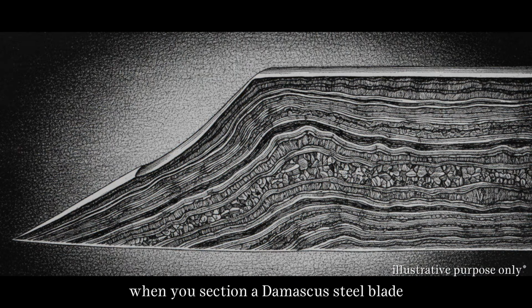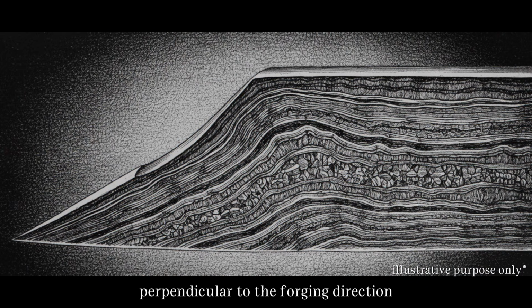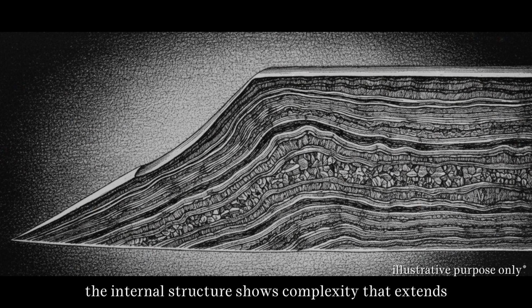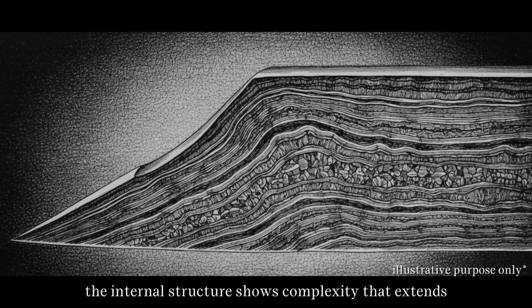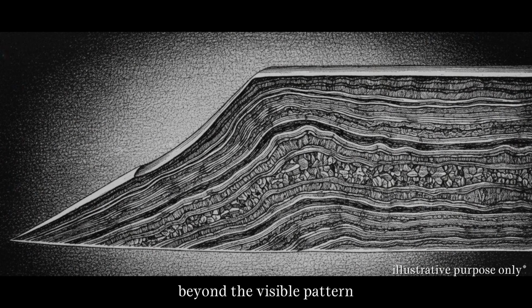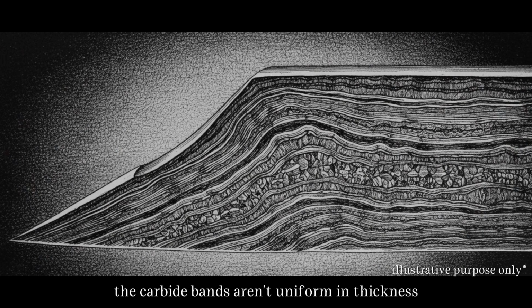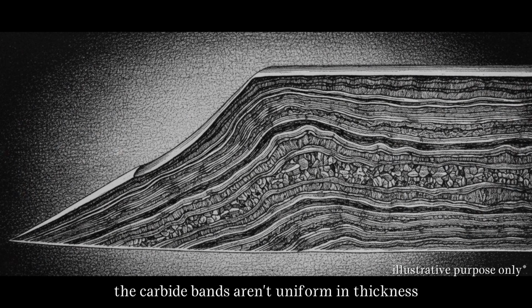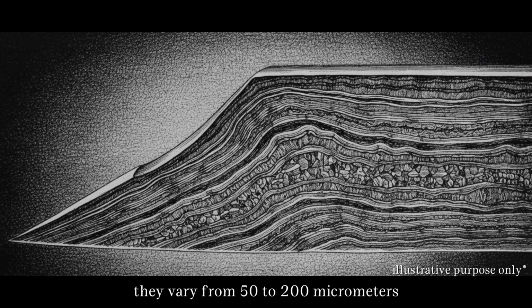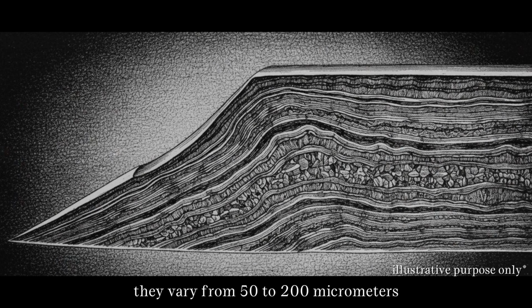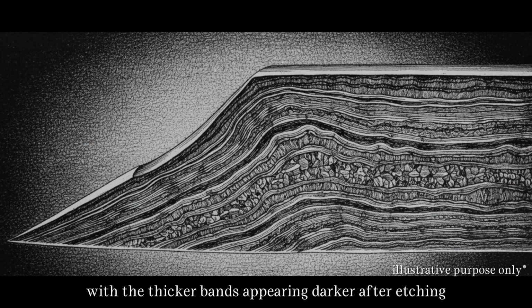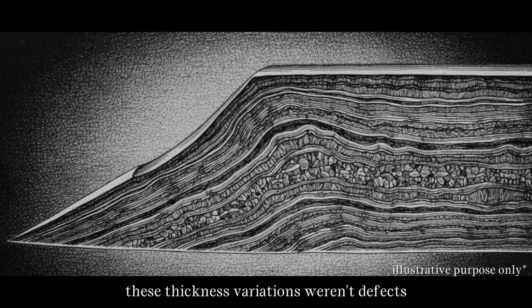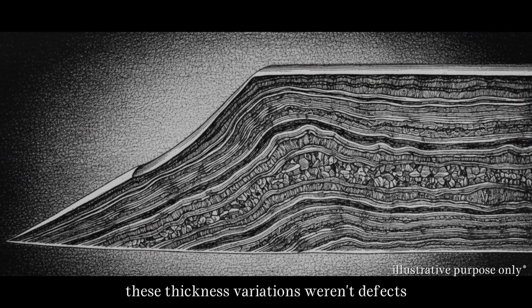When you section a Damascus steel blade perpendicular to the forging direction, the internal structure shows complexity that extends beyond the visible pattern. The carbide bands aren't uniform in thickness. They vary from 50 to 200 micrometers, with the thicker bands appearing darker after etching. These thickness variations weren't defects.